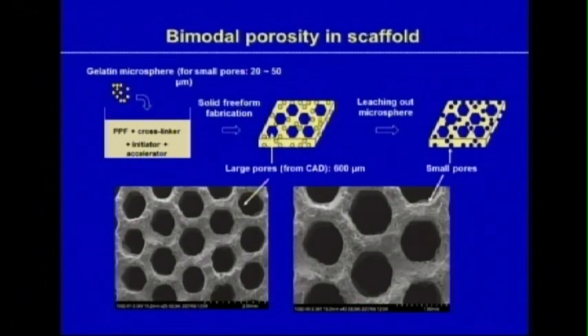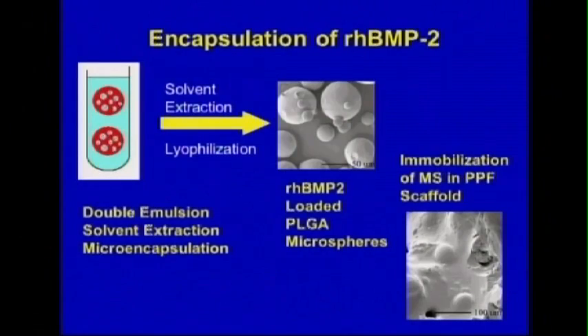They put microparticles that contained, I think we used a FITC dextran as our model. They were able to get them into the pores, and I'll show something about the controlled release from those in a bit. So Dieter Kempen put the molecule of interest, FITC dextran I think, into microparticles, and then immobilized those, that sort of lunar landscape that you see in the lower right. That's the wall of a pore in the scaffold, and the bumps in it are the microparticles.